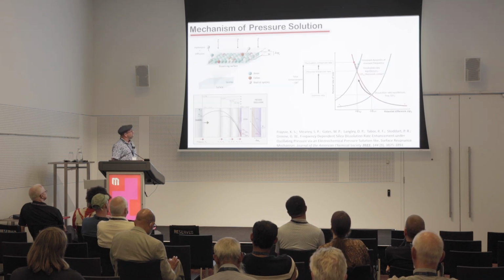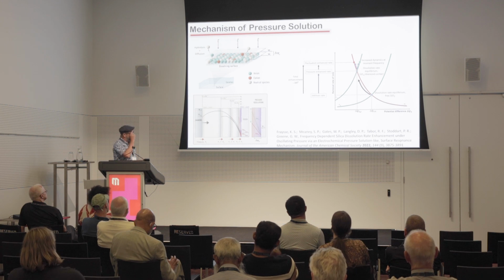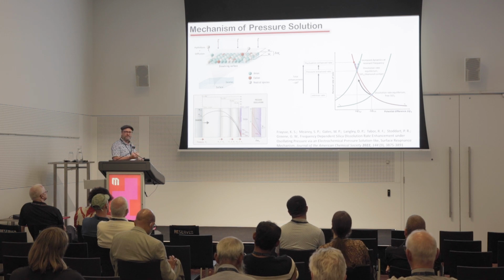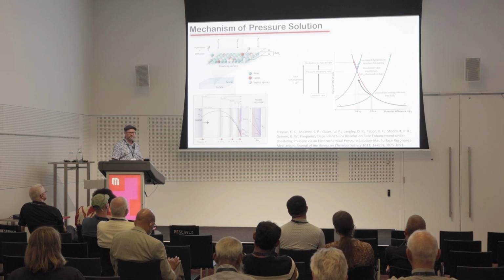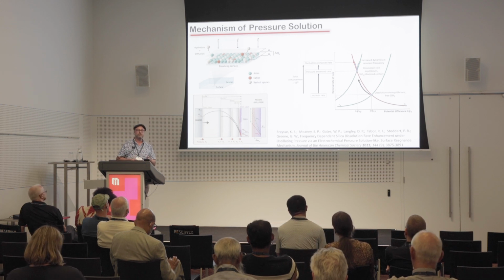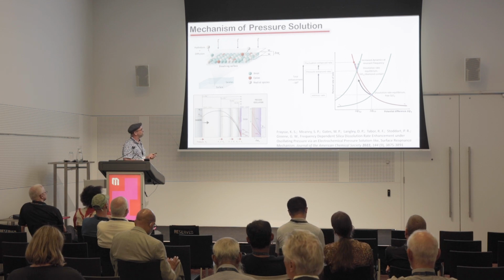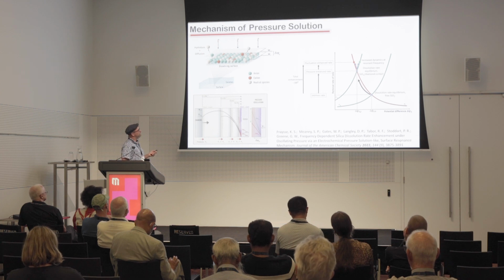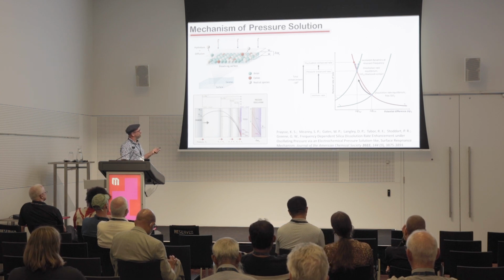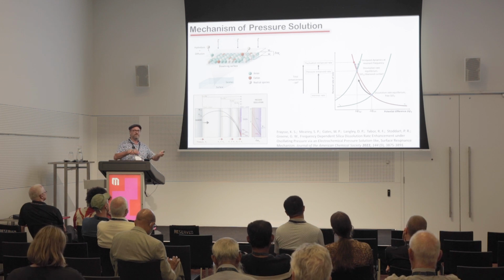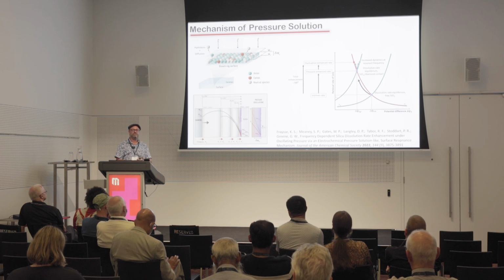All right. So what I'm going to do is sort of give you an abridged version of the pressure solution mechanism. And so to understand it, the first thing we need to consider is what happens if you take a silica surface and you put it into water. Well, the first thing that happens is the surface becomes hydrolyzed, and that process produces a mixture of different functional groups. So you've got anionic groups and cationic groups and neutral species, and they're all being created at that silica surface. Now, for the silica surface to dissolve, you've got to remove these groups from the surface, but the charging of that interface basically produces an electric field.